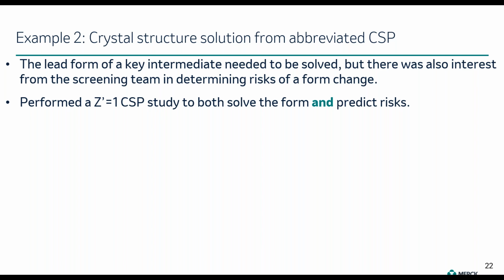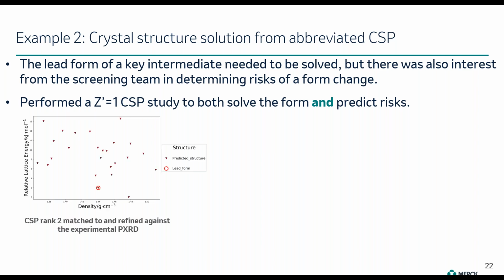So we performed a Z'1 CSP study. So the CSP study was limited to one molecule in the asymmetric unit cell. And in this way, the aim was both to solve the form and predict any risk associated with it. So this is the outcome of this limited CSP study, so this abbreviated CSP study in Z'1.